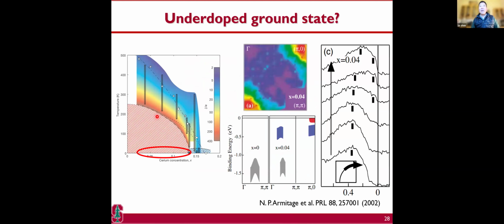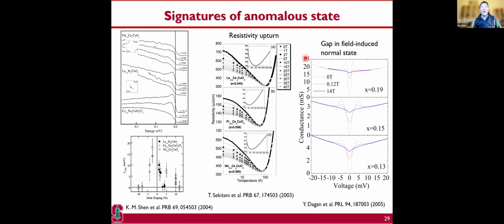Now, this behavior again was seen very early on in Peter's thesis. You can see here the emergence of low-lying states near the antinode. In the underdoped system, generically, this is also seen by Kyle Shen in his thesis work. There's a gapped system and a small gap in this underdoped regime. Kyle, of course, compared with the hole type. For now, we are going to only look at the electron type. Another thing about the electron-doped system in the underdoped regime, at 4%, 10%, 16%, is that there is a resistivity upturn. It's not going insulating, but it's an upturn. It's a peculiar kind of insulating state.